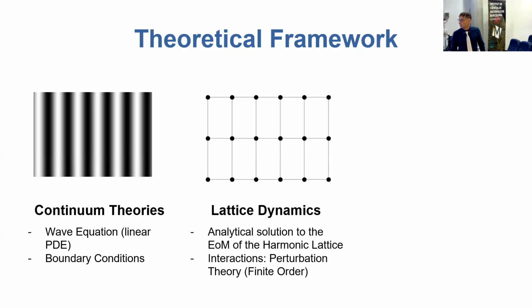A second means of describing thermal transport is provided by lattice dynamics. In this case, we are treating atoms as individual entities, and this is pretty easy: we chase the analytical solution to the equation of motion of the harmonic lattice, and then we treat the interactions between the atoms, or the phonons, or whatever elementary degrees of freedom we want to use, perturbatively. This has a very good side, which means that we can switch on and off the different orders in perturbation theory, meaning that we can, for example, switch off 3 phonon processes and only allow 4 phonon processes to take place, or do the converse. But this is a finite order theory, meaning that we are not describing interactions at every order.